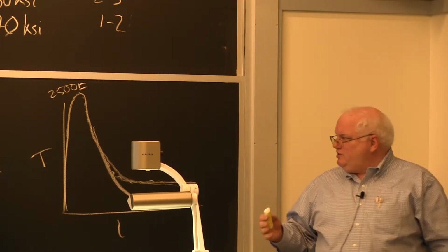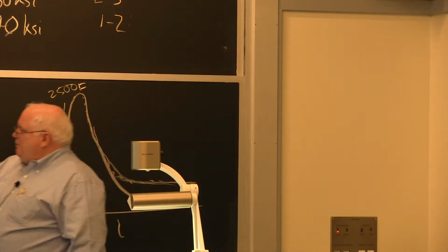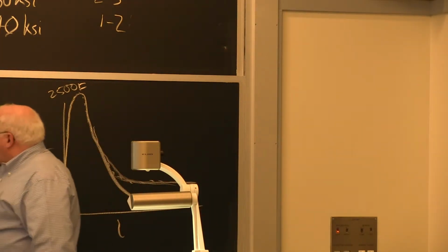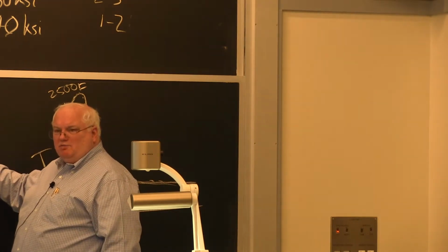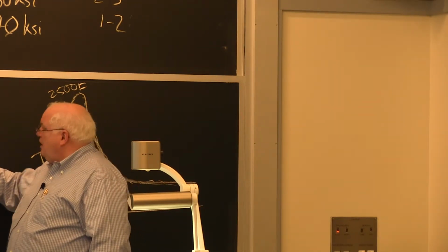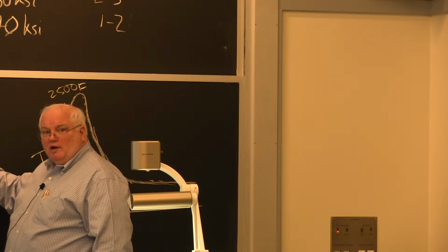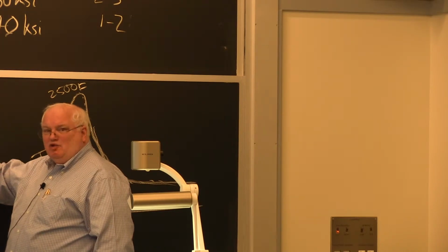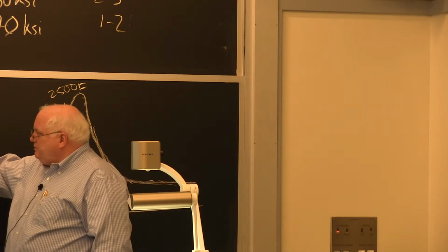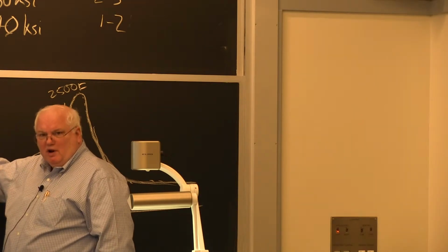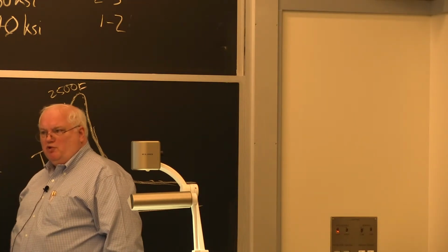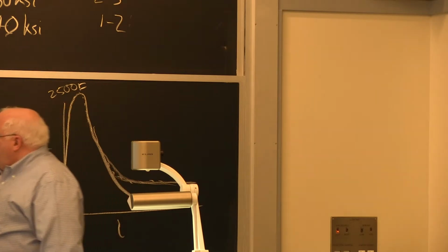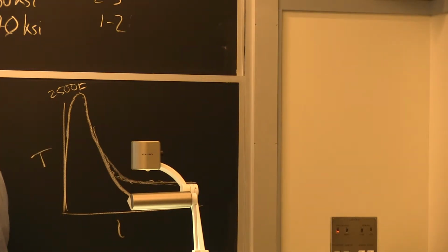At higher temperatures, even in this temperature range, I'm not going to have minutes before I get down to room temperature. I'll have hours before I get all the way down. And it's like doing a bake-out at either 100 degrees or 200 degrees or 300 degrees, whatever temperature I preheated to, right? Above 300 degrees, I'm tempering the steel.